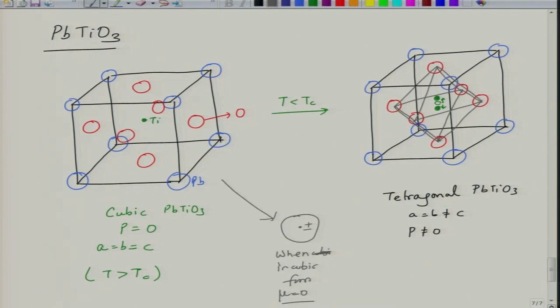Now when you cool it below, the central titanium atoms move up or down. As a result, now the center of negative charge is somewhere here. This is my negative, and the positive charge is either here or here. So let's say I take this one. There is a distance delta, let's say. Delta is a few picometers. Now what we have is a dipole moment of 4 electrons multiplied by delta. So this is a non-zero dipole moment that is developed, and as a result you have a permanent dipole moment, which is called polarization. And that is why ferroelectric materials show a non-zero polarization at room temperature in the absence of electric field, because they have a non-zero dipole moment.